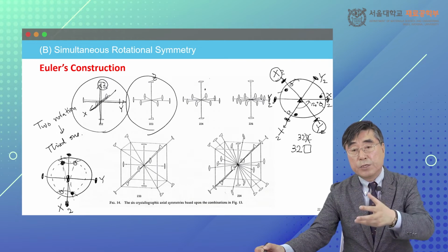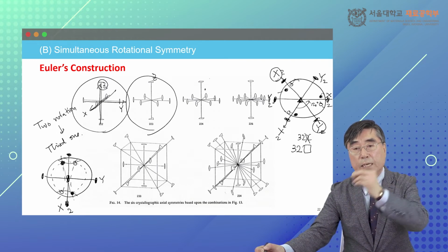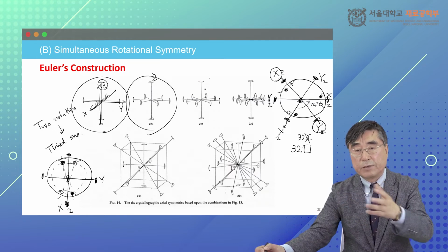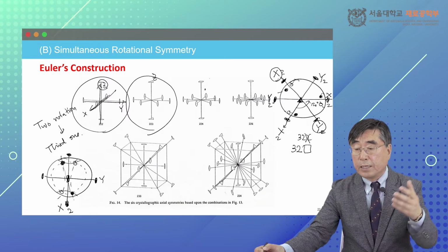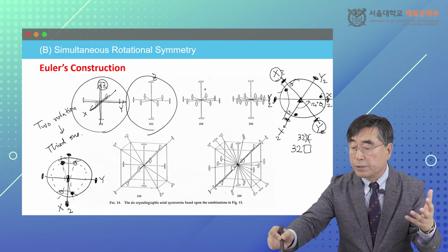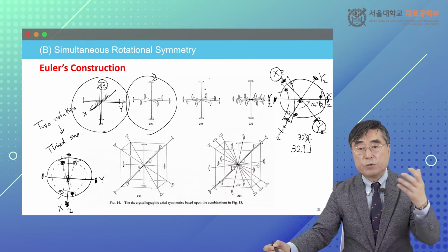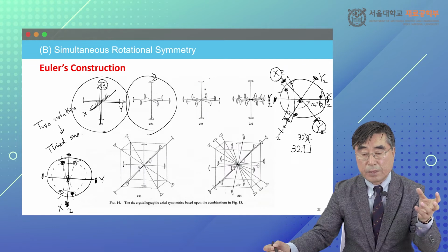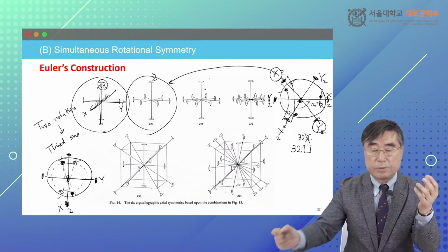This is all rotation, so everything is right-handed. It's just that the upper pole and down pole are different in here. And it generates 6 poles. Now if you do it again, you will see the y-axis operation is already maintained. It's already in there. It does not generate new poles. Okay, so these 2, 2, 3 symmetry elements are possible.